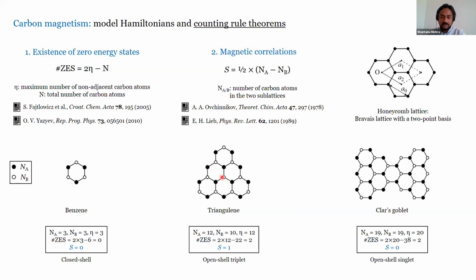So for triangulene, you have a sublattice imbalance. And so the number of zero energy states becomes 2, and you have an open shell triplet case where the total spin is 1. But now coming back to benzene, the existence of spin 0 does not necessarily imply that the molecule has to be closed shell.